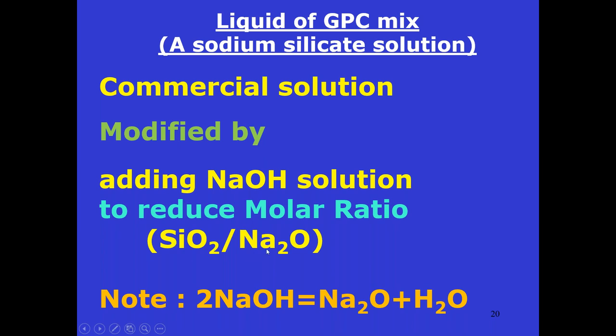This silicon dioxide to sodium oxide ratio is a parameter of the sodium silicate solution. Now in our geopolymer reaction, this ratio should be reduced. Reduced means we can add Na2O. So to add Na2O, we are using sodium hydroxide. So you can see the equation here. That means our purpose of adding sodium hydroxide solution to the sodium silicate is not alkalinity.